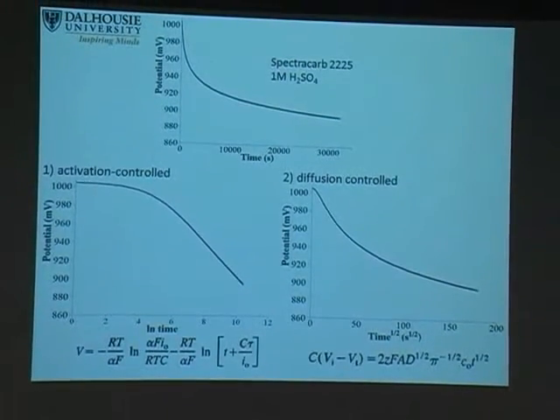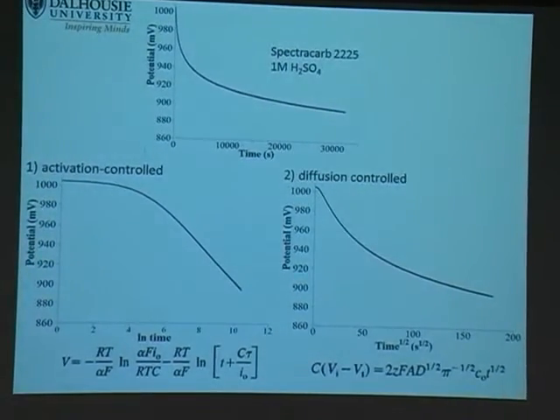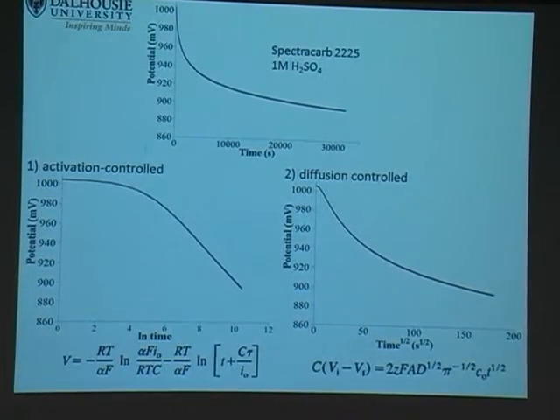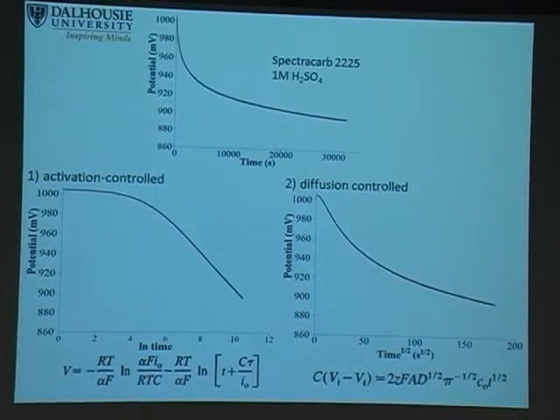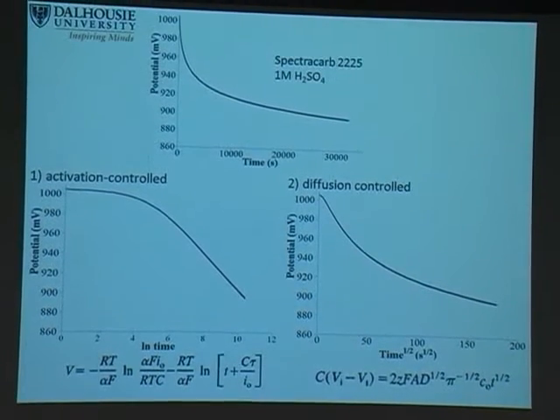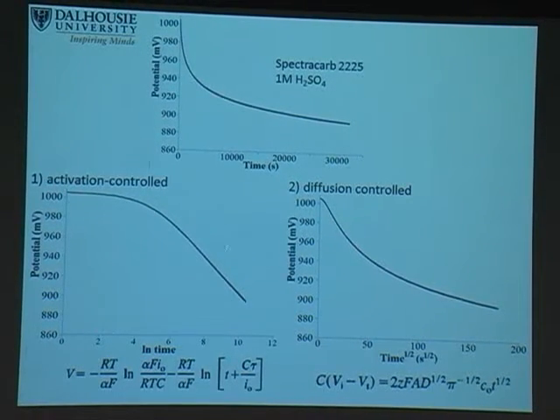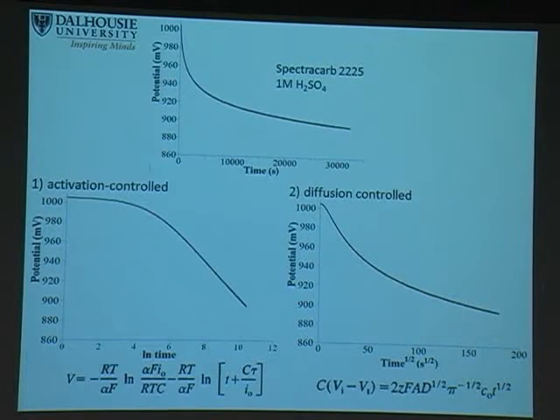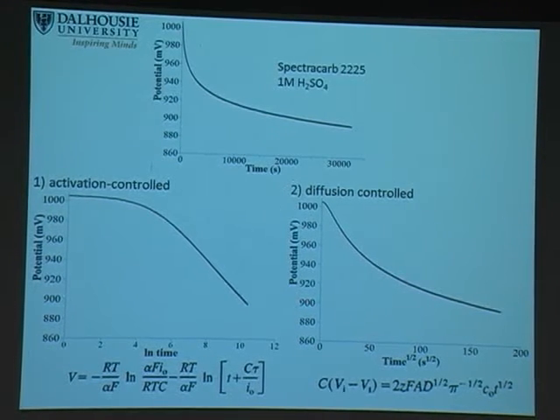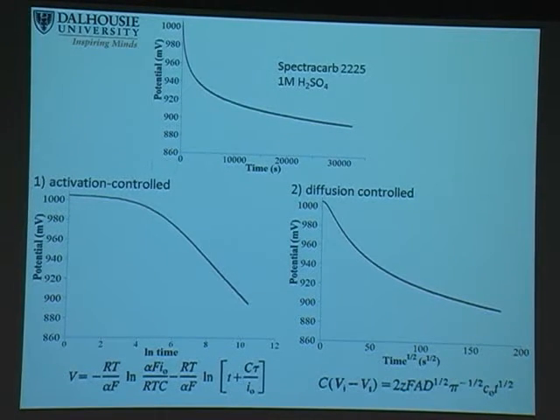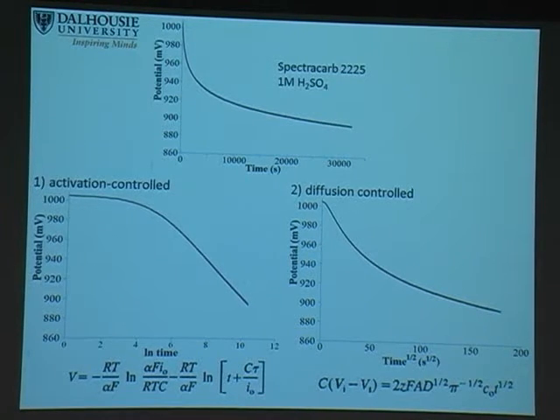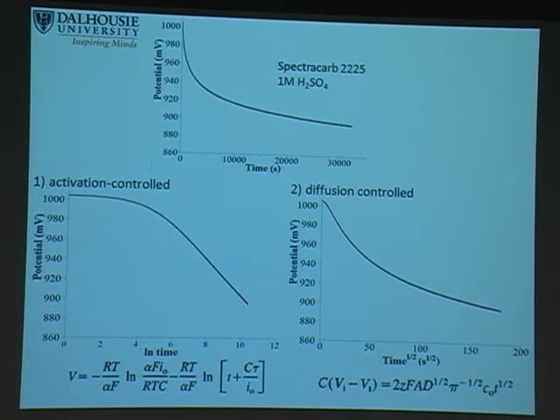So the very first thing we did was plot this versus those two models, and we see very clearly a plateau and a linear drop in potential, which suggests an activation control process. Or I should say, in reality, at this point, it is suggested an activation control process. But what I'm about to show you is that this is not diagnostic for this process. But it is definitely not a diffusion control. And so what that immediately tells us is that whatever the reaction is, it's not an impurity in our cell. It's something else that's happening here.